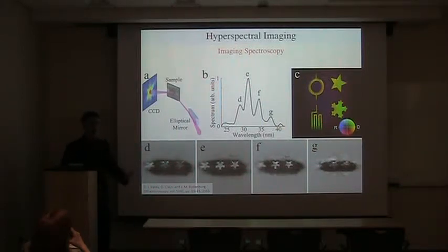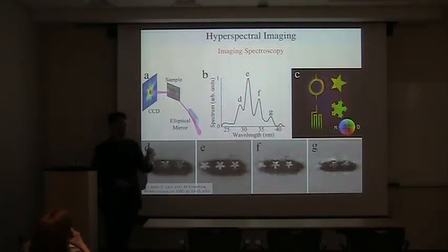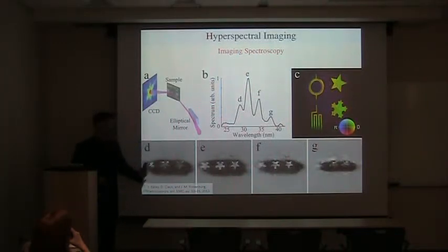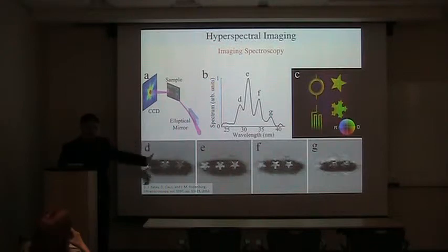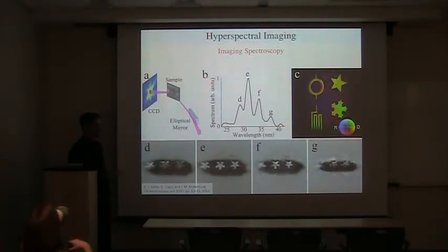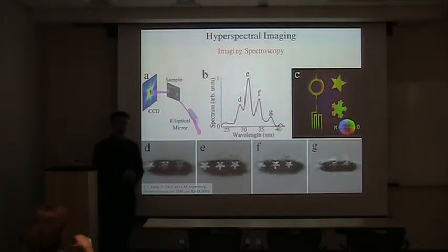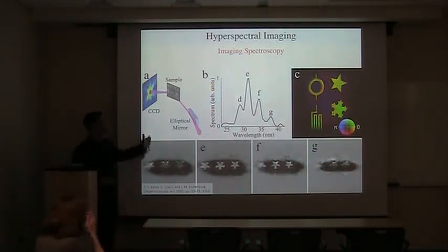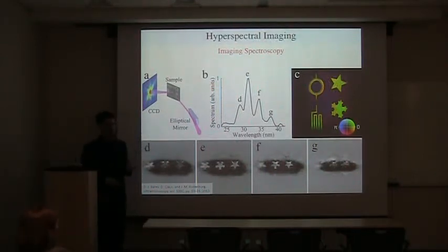So the high harmonic source naturally basically phase matches about 5 harmonics. We can shine them all simultaneously onto the sample, collect an intensity average diffraction pattern, and use ptychography to get an image of each one of these objects for each color. So that is a very powerful microscopy now. We can do real hyperspectral or imaging spectroscopy now. Okay, that's a great tool to have.